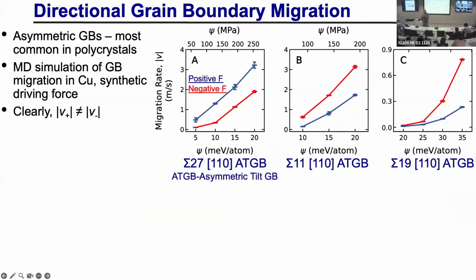And the red and blue curves there are data corresponding to what happens when I put on a positive driving force or a negative driving force. And you can see we have enough data that the error bars are much smaller than that difference. As I said before, when we did this initially, we just thought this was insufficient statistics. So we went to great lengths to make sure that they're statistically significant. And the thing you see in all three of these boundaries is that the migration rates depend on whether the driving force is positive or negative.